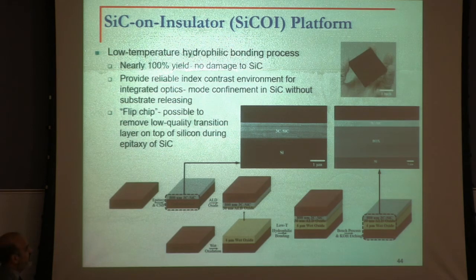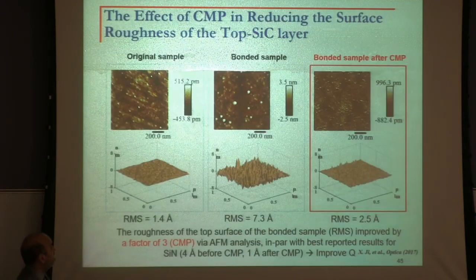So what we did was we used our bonding technology. We put oxide on top of a dummy silicon wafer, and then we bonded this material upside down, and then we removed the silicon. So now when I remove the silicon, the culprit, the bottom layer, will just come on the top. And I can do whatever I want with it. Definitely polishing. So then we did chemical mechanical polishing on the surface to make the quality better. A very simple idea that used our knowledge of bonding in order to bring the quality factor to a record high, as I'll show in here.